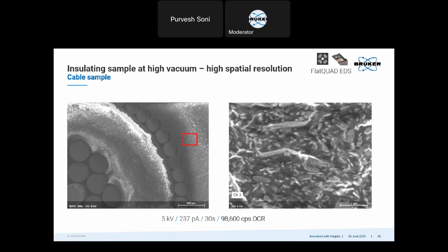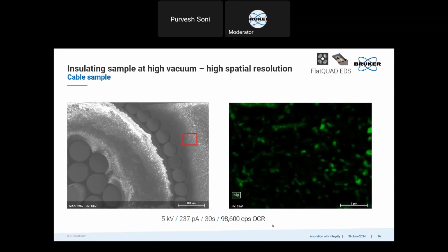Now, if we zoom into this region, then we can see that there were small magnesium particles which were less than 1 micron, so between 100 nanometer and 1 micron in size, and we could resolve this because we were at high vacuum conditions to get the high spatial resolution. And again, super high count rate, and the measurement was only for 30 seconds. And yeah, because of the very high sensitivity, I only needed 30 seconds to measure this region.